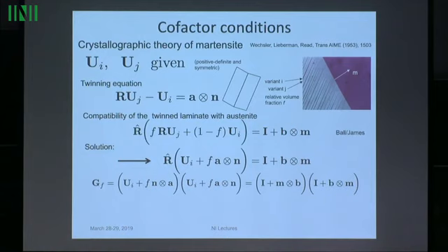Now, if you want to solve an equation like this, again, it's a lambda 2 equals 1 thing: you have rotation times stuff minus identity is B tensor M. You just have to imagine taking the polar decomposition of this quantity, and the rotation could be lumped in with this unknown, and then the stretch tensor in the polar decomposition is the thing that you would like to have whose middle eigenvalue is 1.